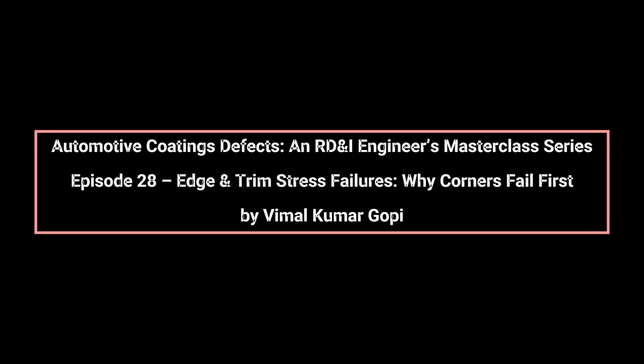Edge failures are also exacerbated by environmental exposure. Water ingress, road salts, and industrial fallout preferentially accumulate in corners and hem flanges. Thin or stressed coatings allow rapid diffusion into the substrate, promoting localized corrosion beneath the coating. This is why corrosion creep often originates at edges, even when flat surfaces remain intact for years.